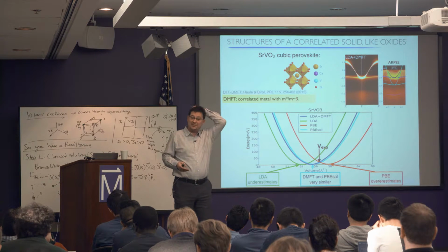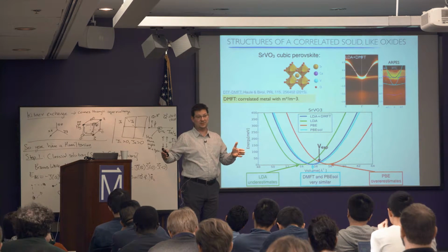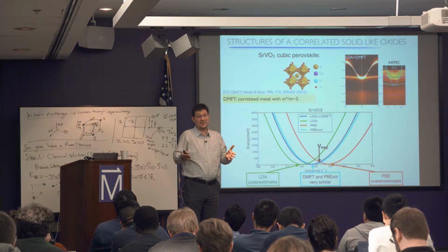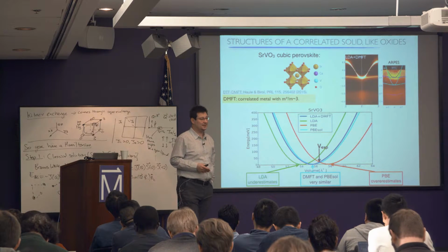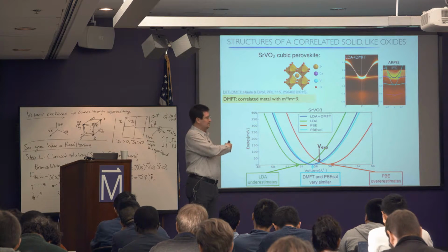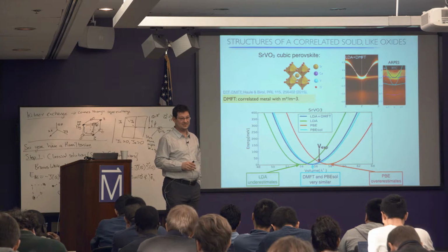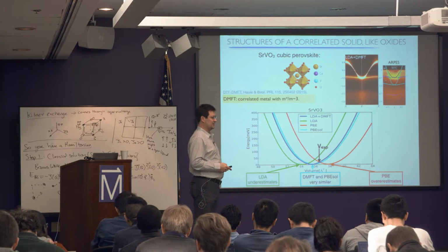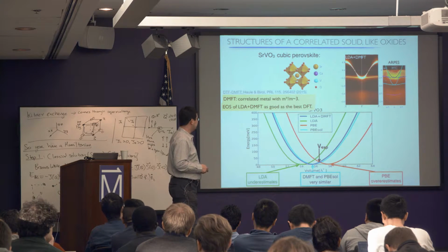Okay, but if you have GGA where the volumes are too big already, and at the same time the spectra are almost identical, that's much more tricky to correct. And in principle, if you had exact double counting for GGA, then it might be able to correct that. But we have double counting for LDA, actually. Okay, so the equation of state is pretty good.